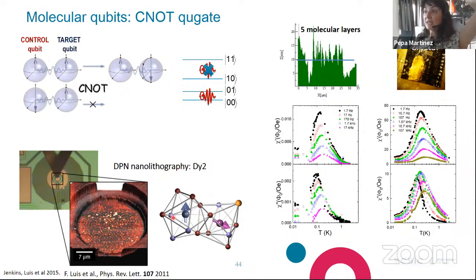These molecules were also delivered thanks to dip-pen nanolithography, forming a very thin layer of just 5 molecules, and our measurements show that the properties of these molecules remain unchanged when compared with measurements performed in bulk samples. This is very nice because it tells us that these molecules still work as a CNOT gate when deposited on surfaces. So now I have finished my presentation.